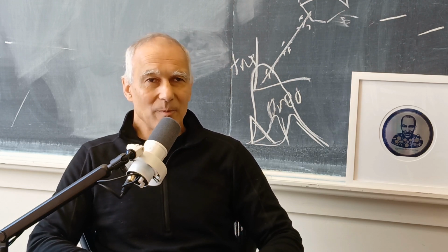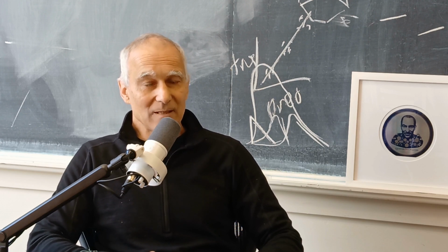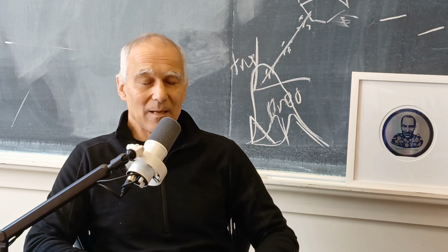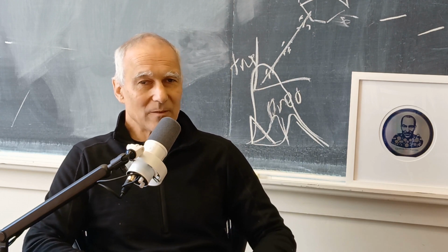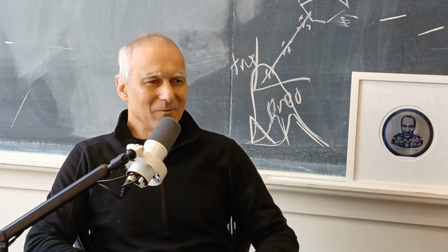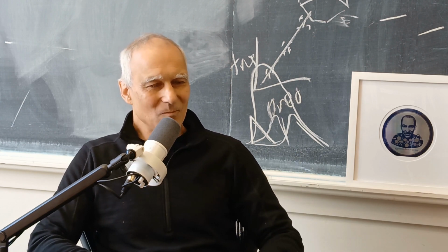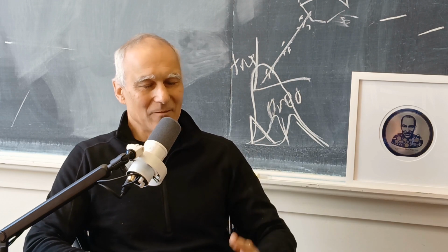Why is it a particle in a box? For a particle that's a few nanometers in size, it's because that electron has an effective mass, which is much lighter than a free electron. So an effective mass of the electron in a, let's say, cadmium selenide semiconductor is about 1/10 of a free electron. And so, you scale from the hydrogen atom to a quantum dot, and you find that the quantum properties of that electron need to be in a box of about 1 to 10 nanometers, and you still have those quantum confined levels.